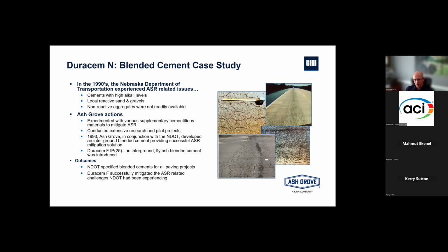Our Louisville, Nebraska plant, which is about 30 minutes south of the Omaha area, has been producing a product known as Duracem F since the 1990s to help combat this problem. How it came to be is that in the 1990s, the Nebraska Department of Transportation, NDOT, experienced significant issues related to ASR. They had the perfect storm of cements that were high in alkali, and their local aggregates, sands and gravels, were reactive. And it's not an arid environment, right? Nebraska experiences moisture throughout the year. Those three things together caused significant ASR-related cracking and damage to their paved surfaces.